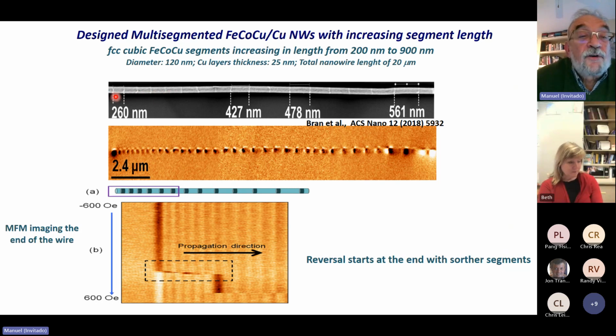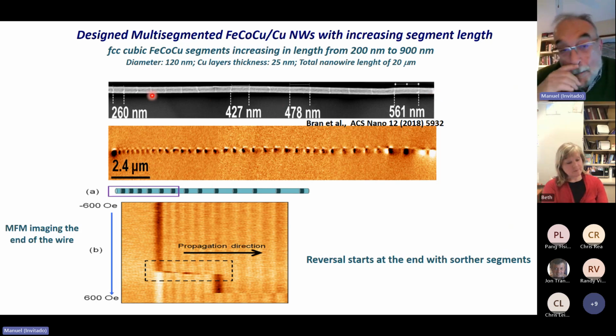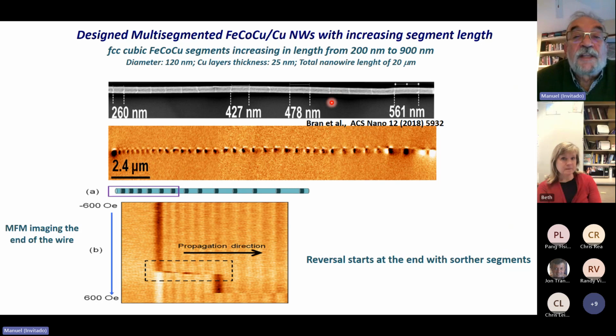You see the length of the magnetic segments, iron-cobalt segment, is small in the left part of the wire and increases, being much larger, continually up to the other end. So this modulation with increasing length of the magnetic segments was introduced artificially during the process of fabrication of these modulated nanowires. This is a magnetic force microscopy image near the end of the nanowire at the remanence.